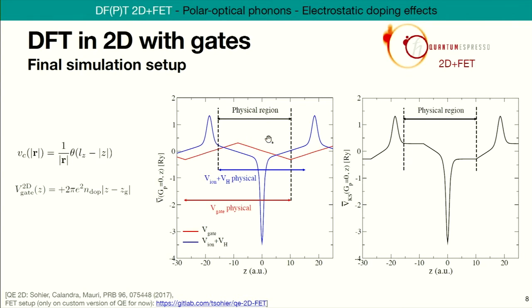And then you have those bumps here on the sides. So those are not real. Those are an artifact of the cutoff that we are doing. And this is because, to understand this, one has to understand that we don't cut off the potentials, we cut off the kernels. And the potential is a convolution of the density of charges and the kernel. And so this cutoff actually moves, slides around with the density. And so what happens here, if you put a test charge, this test charge would feel only part of the system that is here. So it would feel some of the electrons of this material, but not all of them, and maybe not the ions, for example. So there's an incomplete system, and so this is not anything that corresponds to a real system. So we define a physical region in between those bumps in which the potential is what it should be.